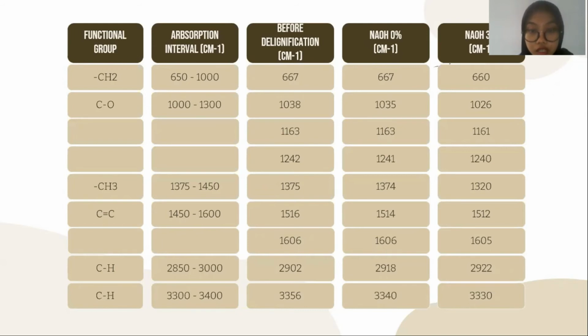In the fiber before delignification, there are peaks at wave numbers 1516 and 1606. The peak indicated the C=C functional group. This functional group indicated a non-cellulose or lignin compound. In the fiber after delignification with 0% natrium hydroxide, the wave numbers of the C=C functional group become 1514 and 1606. While in the fiber delignified with 3% natrium hydroxide, the peaks showing the C=C functional group are 1512 and 1605. So the delignification process does not completely remove lignin, but only reduces it.